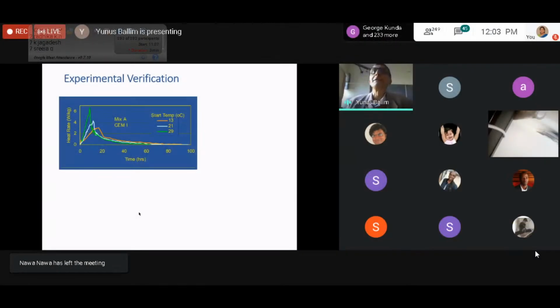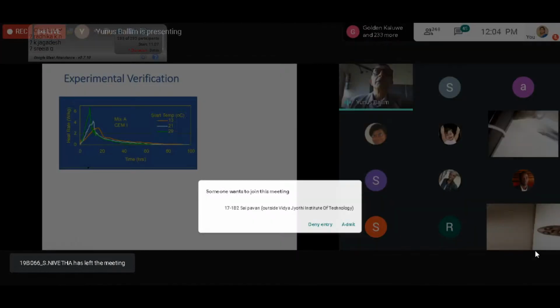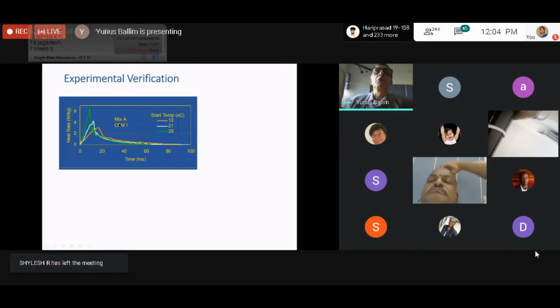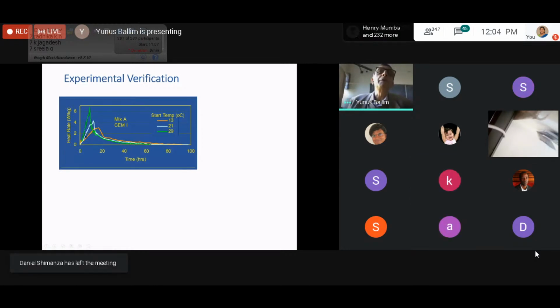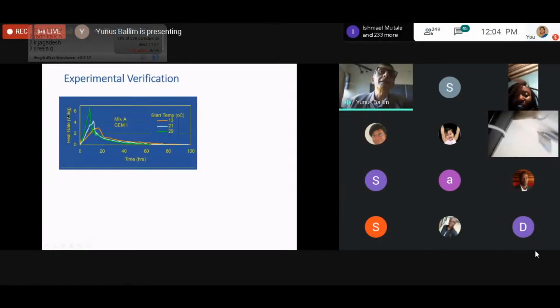And so what we did was we took the same concrete, put it into our calorimeter, but started the test at 3 different temperatures. One at 13 degrees, one at 21, and one at 29. And as I expected, what happened was we got three different heat rate functions. So for the same concrete, with a different time temperature history, we produced 3 different dq by dt curves. When we normalize the x-axis, which is in time, to a maturity axis, and we normalize the heat rate, which is in joules per second, to joules per maturity second, we were able to normalize those 3 curves. And so those 3 curves, in fact, collapsed onto a single curve, more or less, which now allows us to determine a normalized dq by dm.